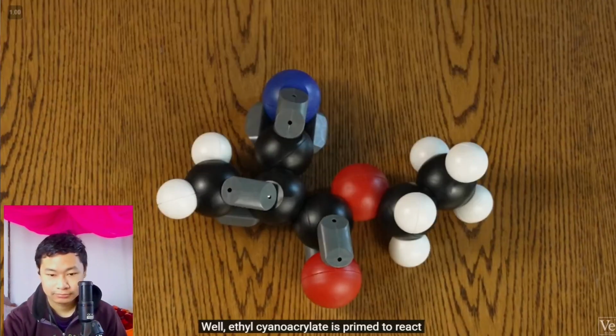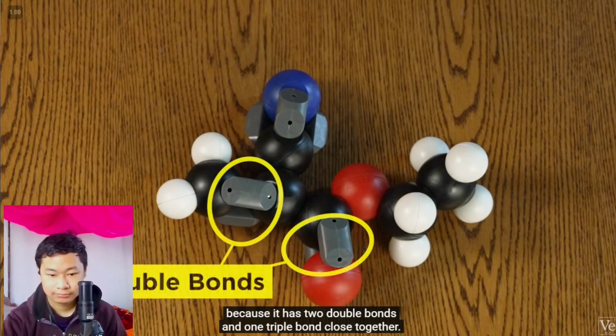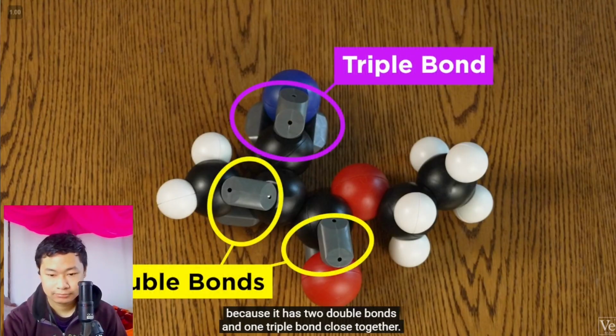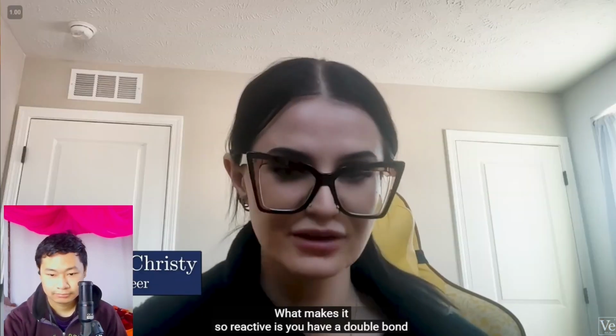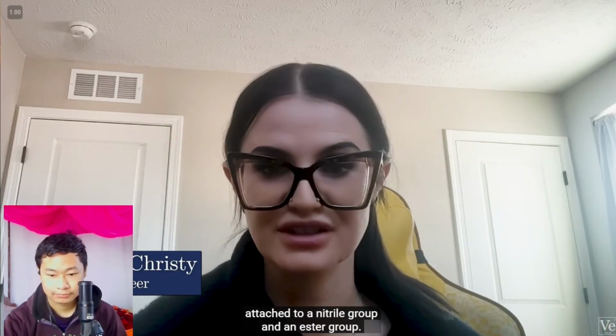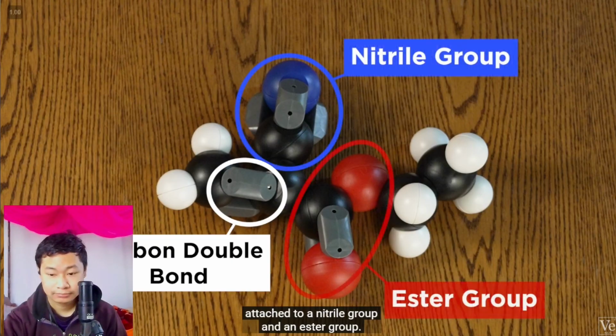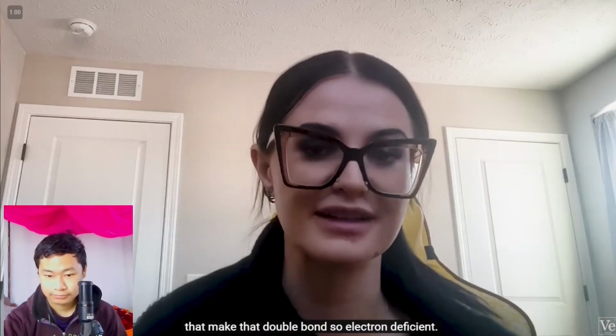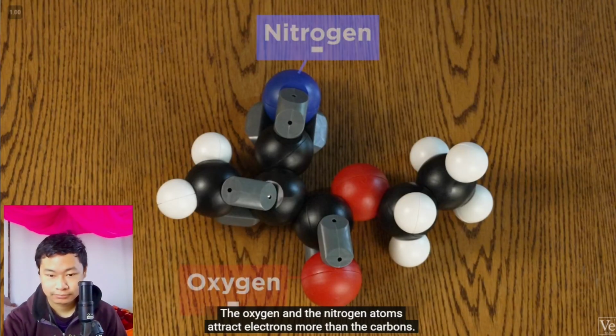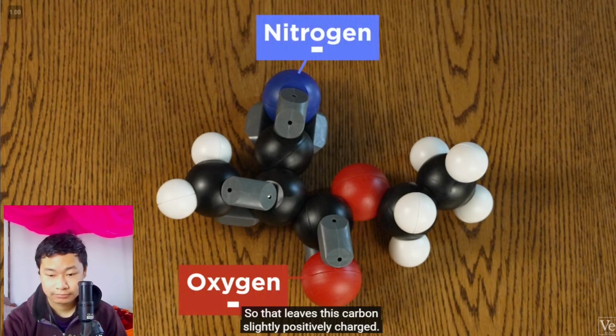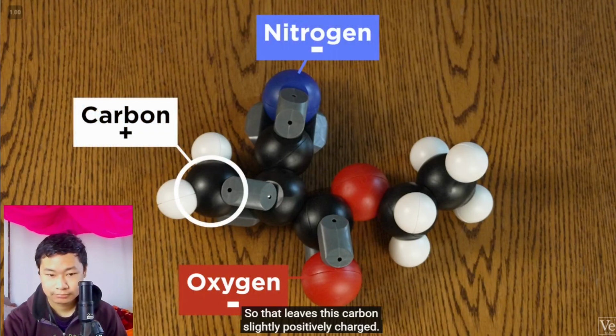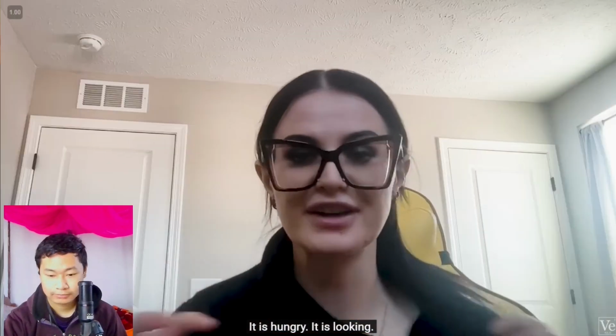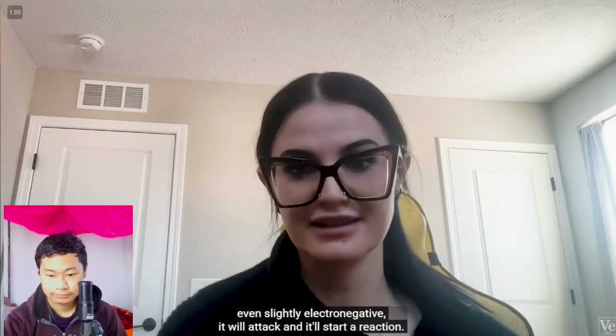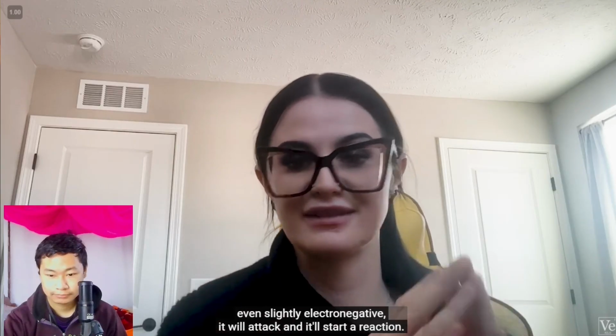Well, ethyl cyanoacrylate is primed to react because it has two double bonds and one triple bond close together. What makes it so reactive is you have a double bond attached to a nitrile group and an ester group. And the unique part about that is the chemistry of those groups would make that double bond so electron deficient. The oxygen and the nitrogen atoms attract electrons more than the carbons, so that leaves this carbon slightly positively charged. It is hungry, it is looking, and anything even slightly electronegative, it will attack and it'll start a reaction.